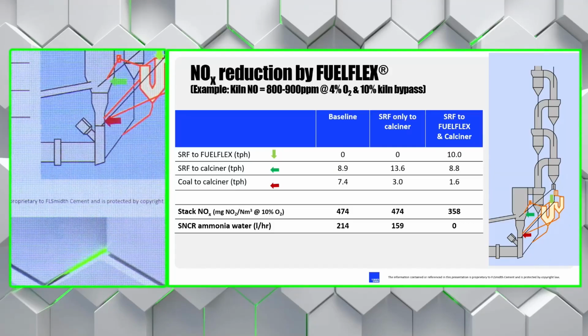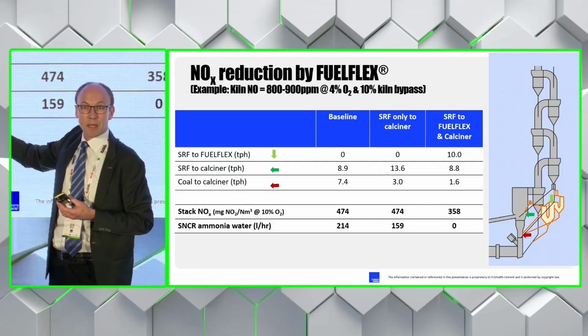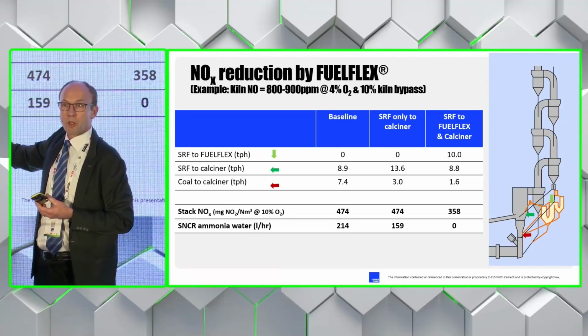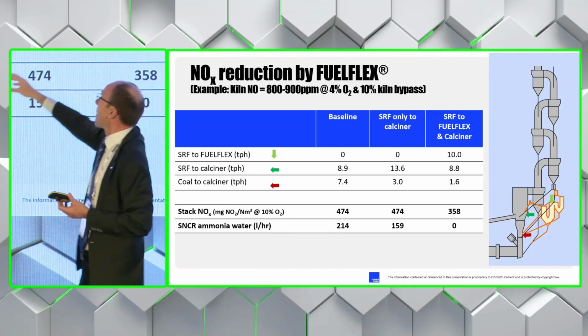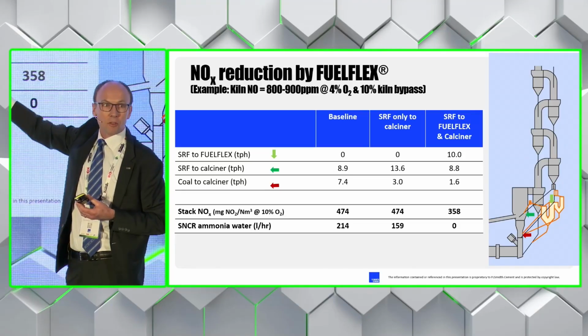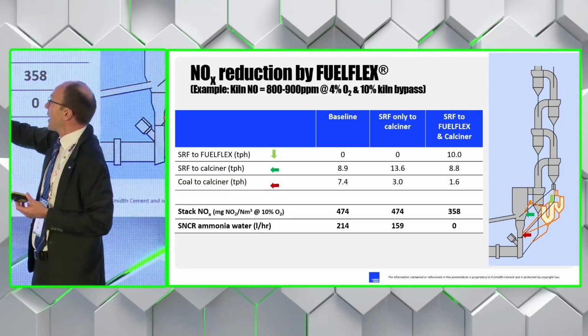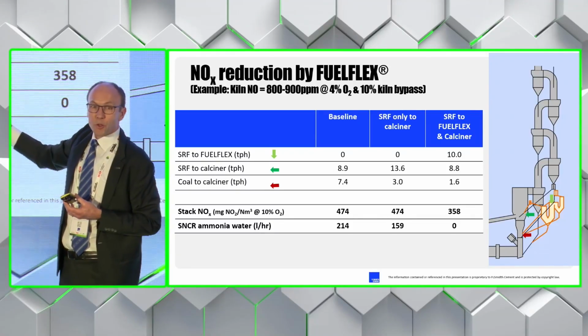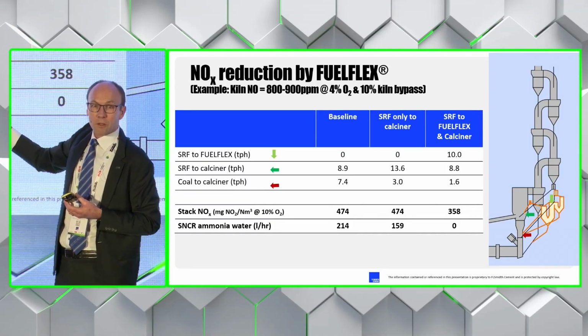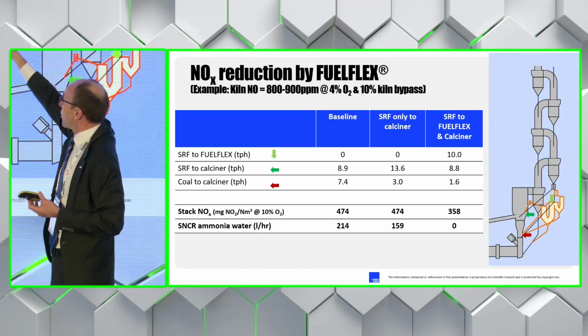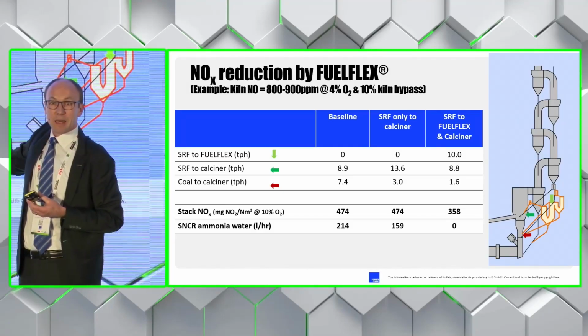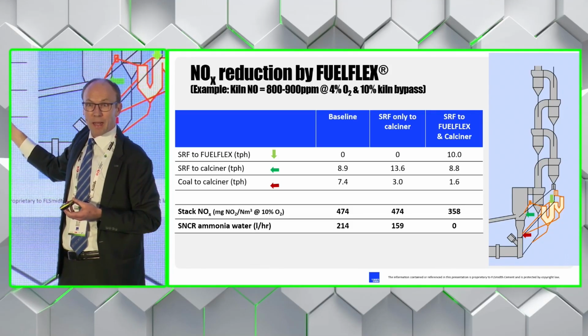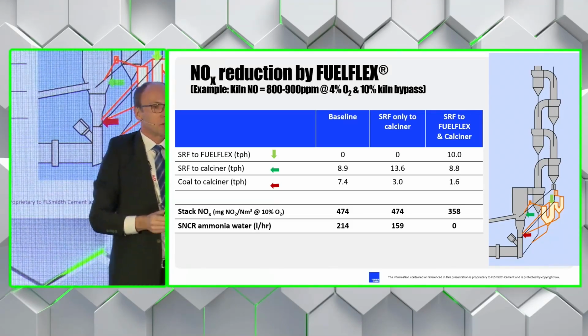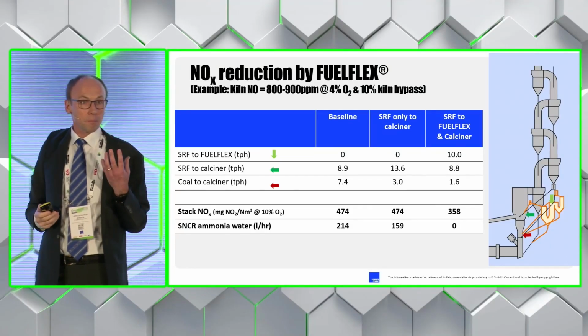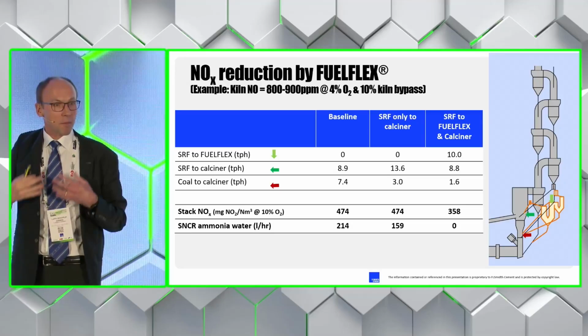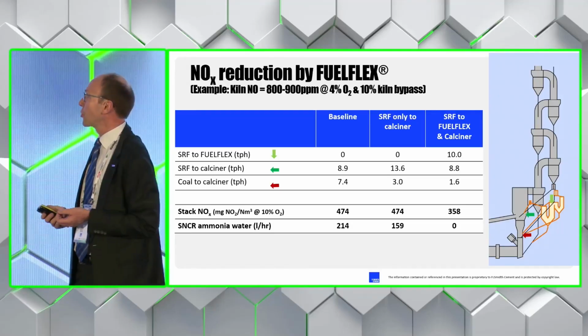What you'll notice here is in the baseline, they're using about 200 liters of ammonia water per hour to comply with the 500 milligram NOx limit. It was actually quite similar when firing the alternative fuel directly to the calciner. A little bit less, but still close to 200 liters per hour of ammonia water to meet the NOx limit. Now, when putting in the FUELFLEX Pyrolyzer, they didn't need to use any ammonia water at all and were operating at a much lower NOx level. So clearly demonstrating how important it is to get the fuel to be very reactive, to be able to reduce the NOx.